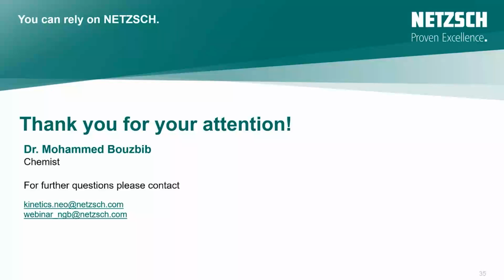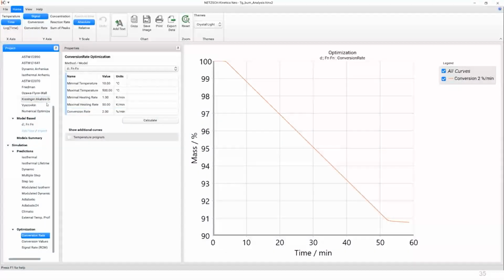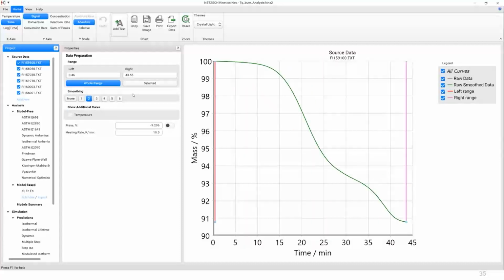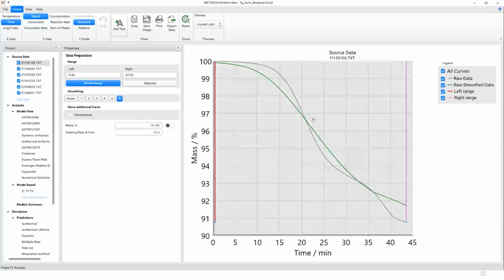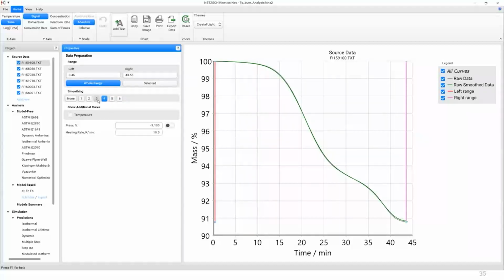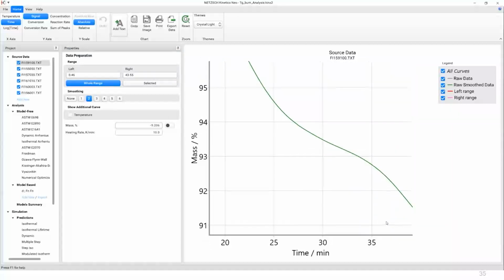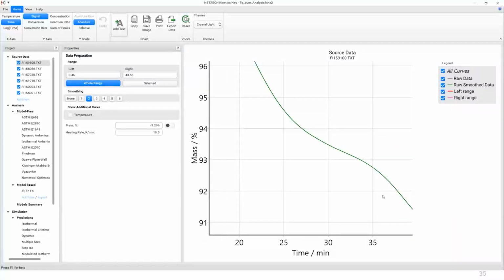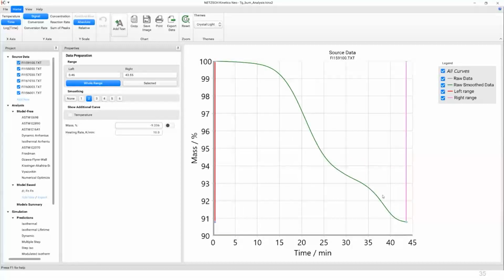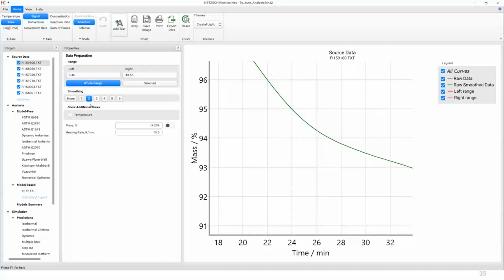Yes, it's the degree of smoothing. It's only the degree of smoothing. So just a second, maybe I will take back the software. Just a moment. So here, for example, if you see the 6, it will destroy the experimental data. But we don't need to destroy the experimental data, we just need to do the smoothing. So that's why we start to decrease, down to 3 or 2. This is the best smoothing for us. We would like just to remove the noise of the signal. So this is why smoothing is important in this case. We use it only when we have a bad quality of the signal. But in this case, our signal was quite perfect. So that's why I made just the smoothing of degree 2.